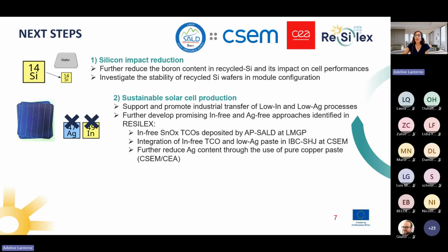Another next step is to further develop promising approaches that have also been developed in the project and not presented here, where we could reach indium-free solar cells or silver-free solar cells. And for some of them, we have very promising results. For instance, at LMGP, they develop indium-free TCO layers with new techniques for the deposition, which is AP-SALD. And so we had promising results with these layers.